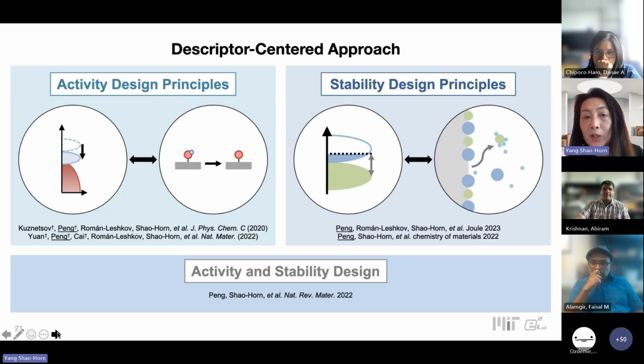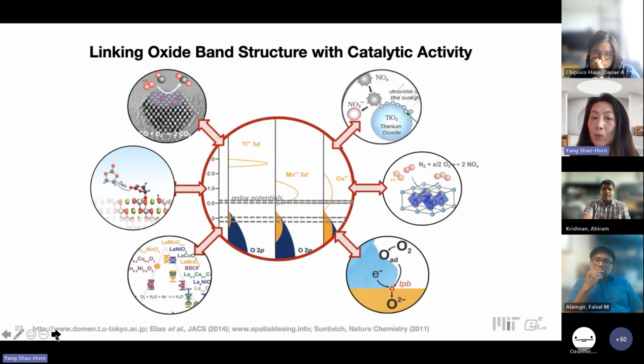So over the past decade or so, we have been developing this so-called descriptor-centered approach, relating the electronic structure of oxides, looking at the oxygen p band center relative to the Fermi level, to the binding of reaction intermediates. We can also relate this electronic structure, the stabilization of the oxygen p band relative to the Fermi level, to the stability of the material, such as stability against dissolution of ions, and also stability of the surfaces reacting with, let's say, CO2 and water, and through which we can utilize electronic structure to develop optimized activity and stability. And over time, we can go beyond one particular reaction, let's say oxygen evolution. We can correlate the covalency, or the electronic structure, to a number of reactions, such as CO oxidation.